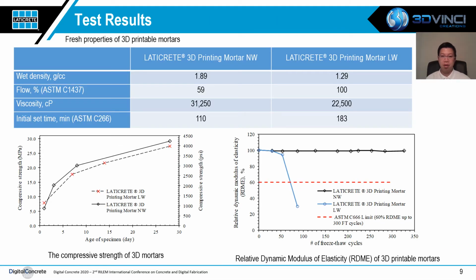Two types of 3D printing mortars were developed in our lab, normal weight and lightweight. In this slide, we can see the test results of the fresh and mechanical properties and the freeze-thaw performance of both materials. The lightweight 3D mortar is found to be less viscous than its normal weight counterpart, despite having a comparable water percentage ratio. In terms of the strength, the normal weight has slightly higher compressive strength than the lightweight mortar. With regard to the freeze-thaw performance, the normal weight material has performed excellently, with a relative dynamic modulus of elasticity above 95% after 350 cycles.